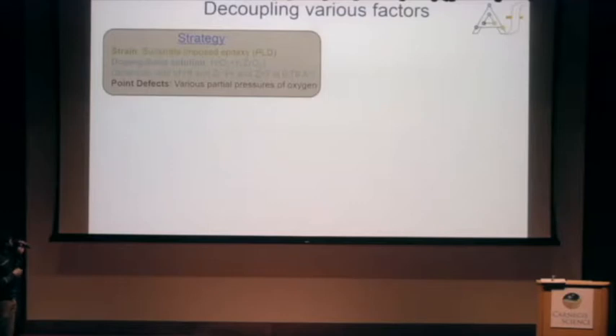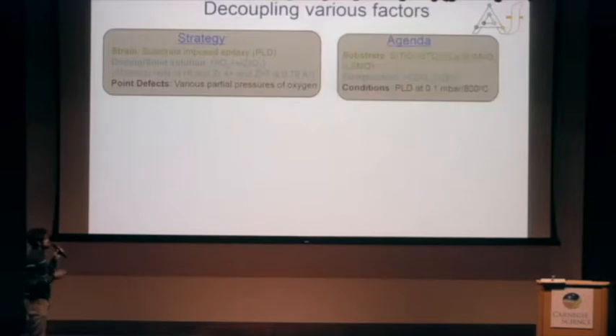So our strategy has been to, ideally, design clean experiments where we study the effect of strain by changing the substrates. We study the effect of doping, specifically by choosing the hafnia-zirconia system, because zirconium has the same exact size as hafnium. So putting in zirconium in hafnium positions doesn't induce any internal strains, unlike, say, yttrium or lanthanum or some other ions. And also, we can study the effect of point defects by varying, in this experimental setup, the oxygen partial pressure, for example.